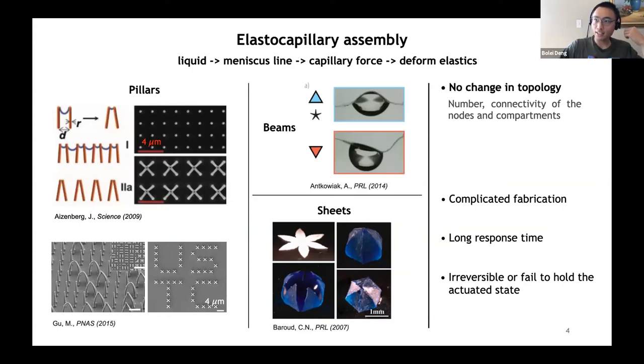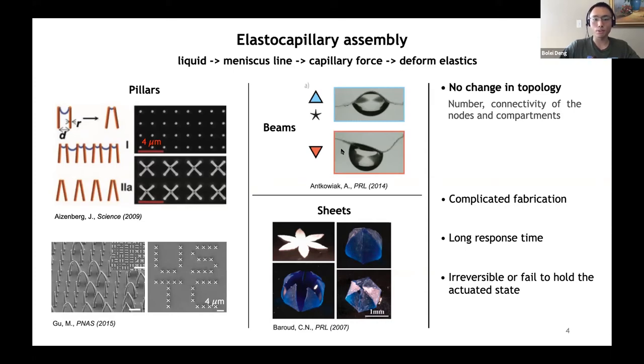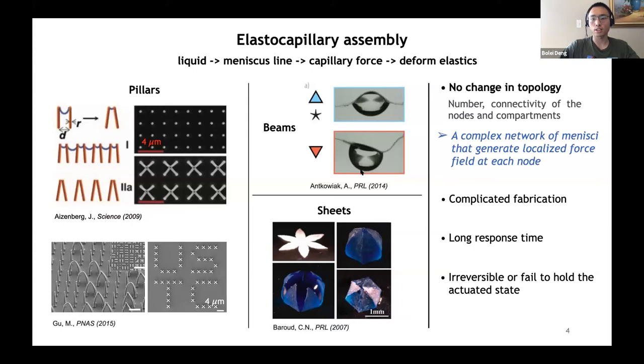Interestingly, this can be solved by using simply a droplet of liquid through the elastocapillary effect. When liquid evaporates, it forms a meniscus line which exerts capillary force. Normally these capillary forces are too weak to deform the structure, but if the structure is very small or very compliant, the capillary force is significant enough to serve as a powerful tool to deform or even assemble the structures. Finally, adhesion between the structures may hold the reconfigured shape.